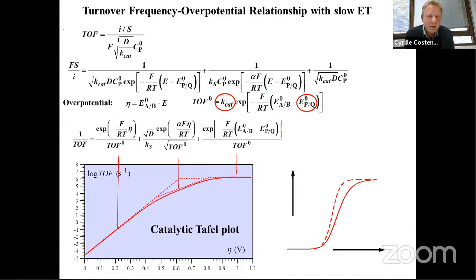Of course, it's not always the case, and sometimes you have some sluggishness for the electron transfer between the electrode and the catalyst. And in that case, as you can see from this schematic CV here, instead of having the S-shaped CV, whose shape is governed by the Nernst equation, you have something which is more sluggish here. And the problem is that in that region here, the current is no more controlled by the catalytic reaction. As you can see here, the current will be controlled by the rate constant for electron transfer between the catalyst and the electrode.